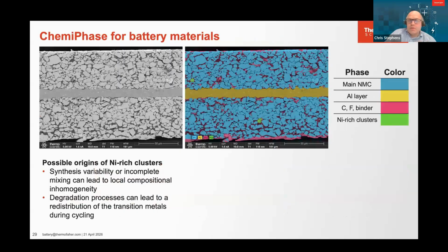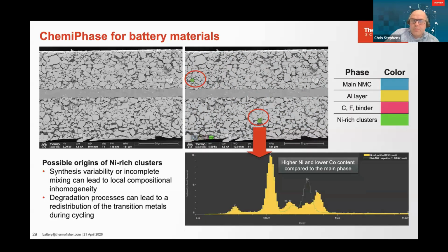What you will see is what something typically would look like. On the left is a typical, in this case, backscatter type image from an in-lens detector. And on the right, we can understand what we have. So you have the main NMC region, you have the aluminium layer, you can see the binder, but you can also see two little green regions that the system has automatically identified as being different. As you click on one, you'll see the system is able to identify from those regions that you're going to have a slightly higher, in this case, nickel composition and a lower cobalt content. And this tells you something about the material itself.